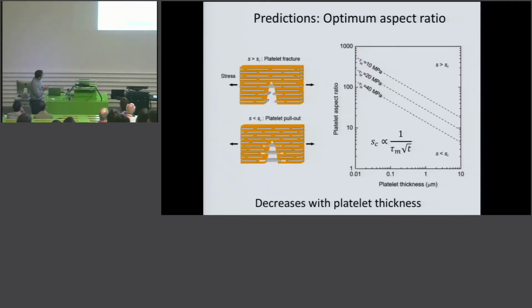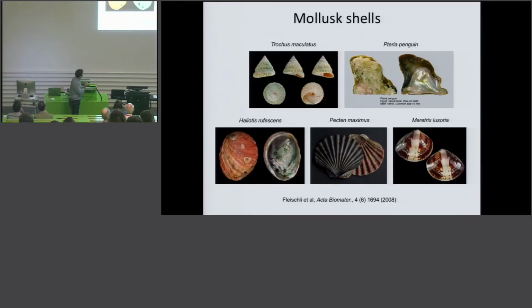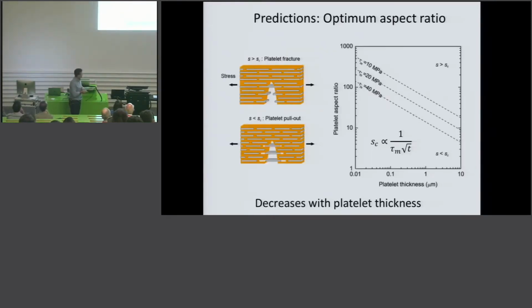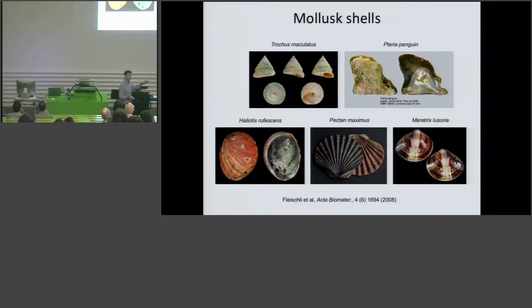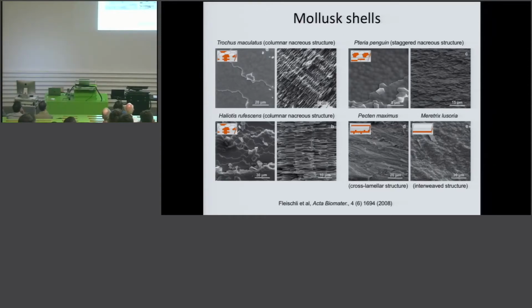And now we can take this very simple relation and plot the critical aspect ratio, which you see here, as a function of the platelet thickness, which you see here, for 4 different shear strengths, right? These are these lines, with a slope of, in a log-log plot, minus 1/2. And so if you do that, and we don't really know what the shear strength is, we can get these different lines. And what's really interesting now is to look into different seashells with different platelet thickness and see where they would fall in that plot. And this is what my colleague Ralf Spolenak did a while ago. So he took all these different seashells, looked at the microstructures, and interestingly enough, they have all different thickness of the platelets, and added them in the plot.